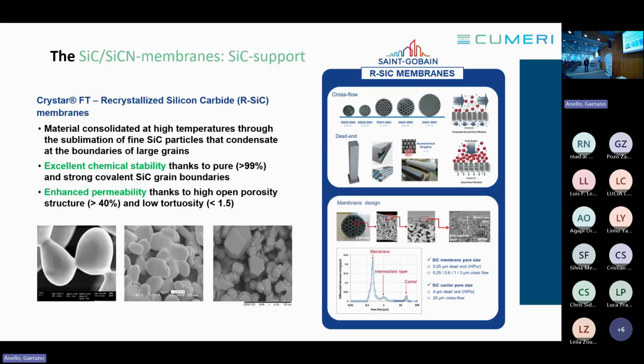This is a portfolio of the Saint-Gobain production line. They are using recrystallized silicon carbide, which has a very high purity and is therefore very chemically stable, and it has quite high permeances because the open porosity is bigger than 40%, which is quite high, and also the pores are quite straight. They are preparing membranes in different geometries, mostly as tubes, from single channel tubes to multi-channel tubes of different diameters and numbers of channels. In the bottom line, we can see the pore sizes they are able to prepare. You can see that the carrier, the substrate, has pore sizes up to 10 microns. Then they have an intermediate layer, and the final membrane layer they are able to produce. This is a range of 250 nanometers.